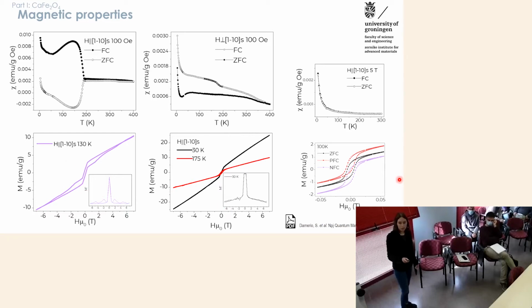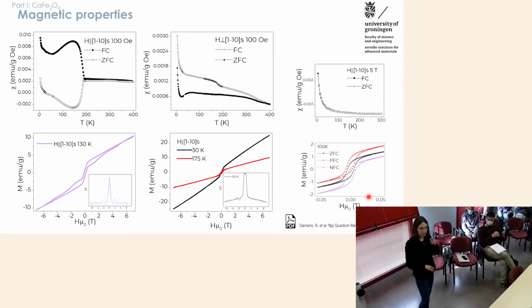Another interesting feature is that if we measure these loops by positive field cooling or negative field cooling, we can have a vertical shift of the loop, which is usually quite unusual. Usually there is more of a horizontal shift when you have coupling between an antiferromagnet and a ferromagnet, but here we also have a vertical shift of these MH loops. So we wanted to know more about the magnetic properties of the system,